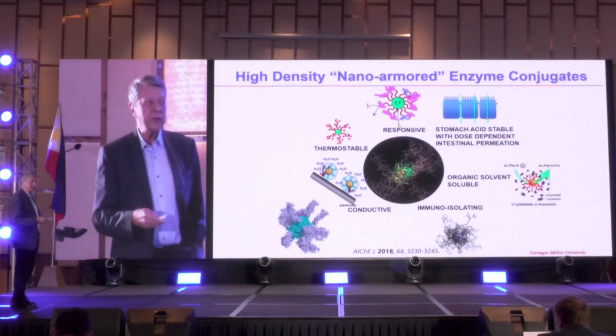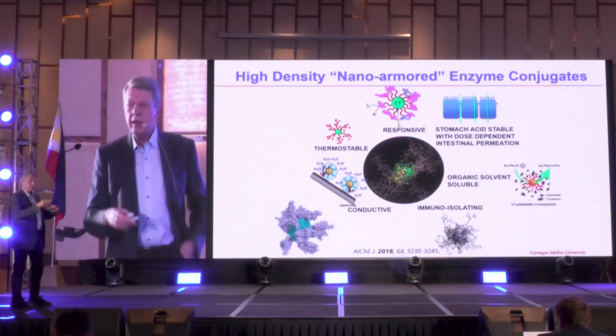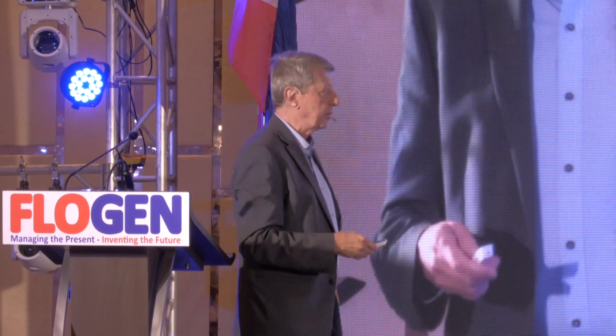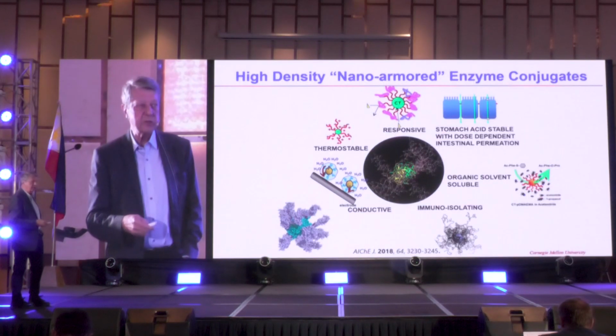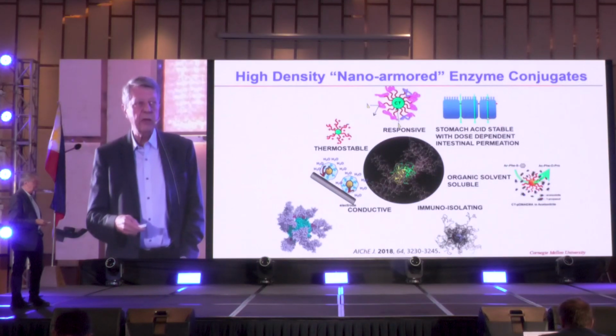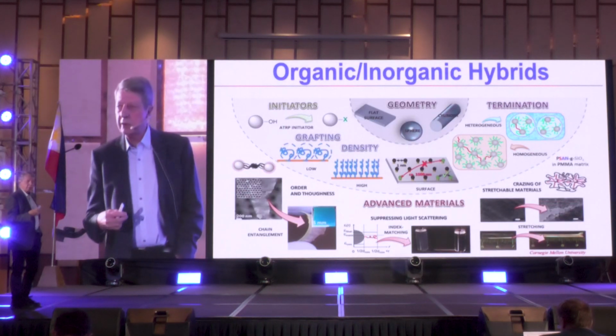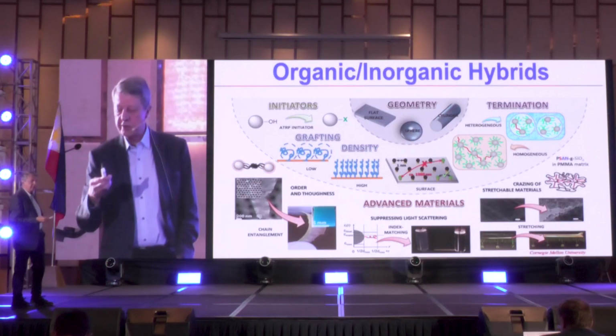So you could see here what happens if you decorate this protein with an armor of a polymer layer. First, they will become immunoisolating because antibodies cannot detect this foreign body. And in that case, it survives for a much longer time. And you can run the reaction in organic solvents because enzymes are fantastic catalysts, but sometimes they denature in the environment, which is in fact very unfriendly, and they unfold. This polymer layer helps to refold them back to original structure. So these are some possibilities, but we extend that to materials which we heard from a previous lecture, to composites.